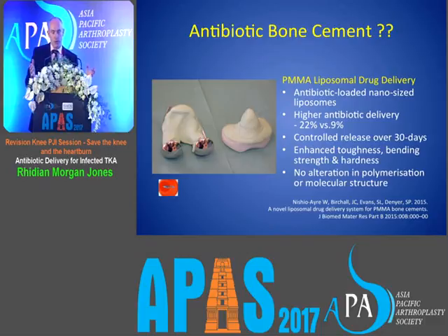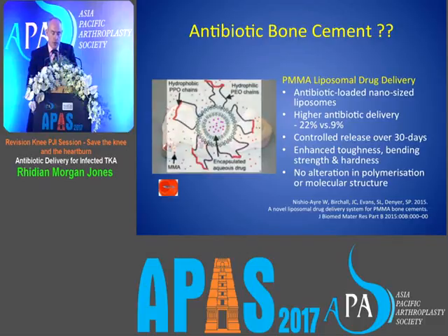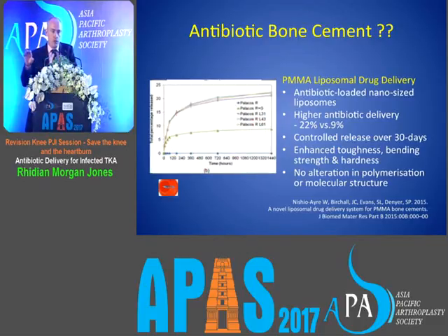What about bone cement? We come full circle. A group of my colleagues in Cardiff have looked at liposomal drug delivery. So we add nano-liposomes to the bone cement, and that doubles the antibiotic release and prolongs the release of antibiotics way beyond 30 days without altering the structure and integrity of the cement. So there is, if you like, cement fighting back.